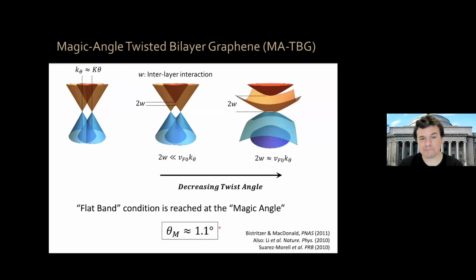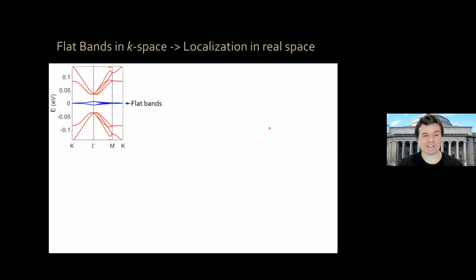Now, this is a cartoon. Okay, let me show you. This is an actual calculation of the electronic structure of magic angle graphene at 1.1 degrees. Okay, as you can see, there is this set of flat bands. That's the flat band condition. These are the other remote bands in the band structure. And these flat bands, okay, they're not completely flat. There's a little bit of dispersion, but they're much, much flatter by orders of magnitude than the original graphene electronic